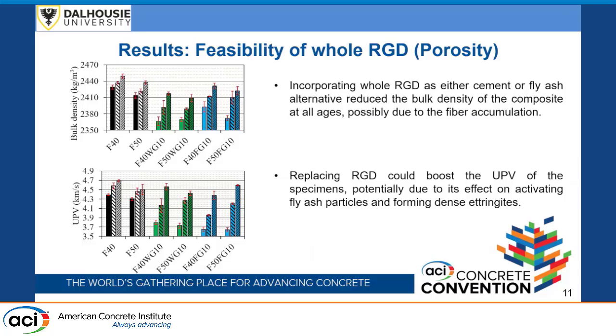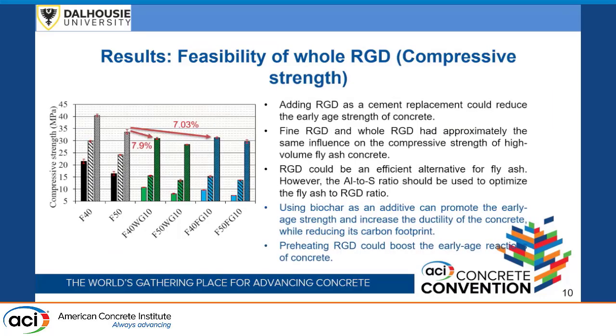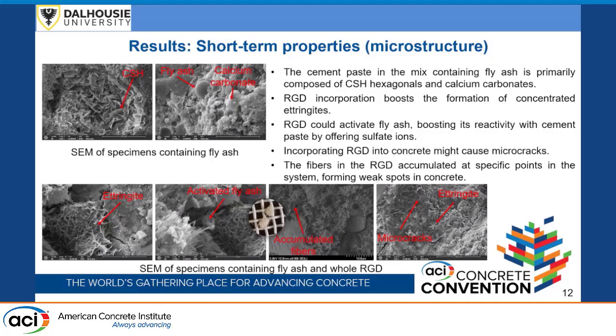However, when we go for UPV, we can see the UPV of the system is almost consistent with the F50, which shows us the potential of RGD in both shapes as a replacement for fly ash. And when we go to microstructure, you can see the microstructure of the specimens containing only fly ash and specimens containing fly ash and whole RGD.